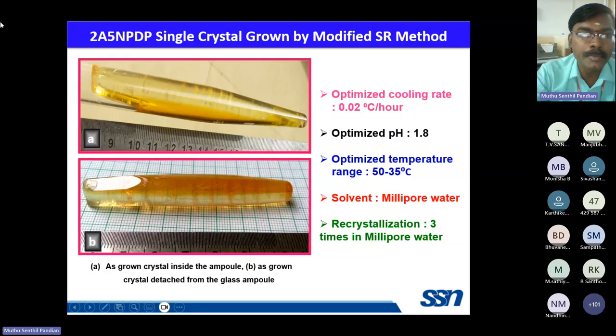And this is the 2-amino-5-nitropyridinium dihydrogen phosphate single crystal for nonlinear optical application. This is the crystal inside the glass sample, and this is the crystal without the glass sample. So this we have grown by the slow cooling method. We prepared the solution at 50 degrees Celsius, and we reduced it to 35 degrees Celsius with a cooling rate of 0.02 degrees Celsius per hour. From this slow cooling SR method, we have grown this large size single crystal.